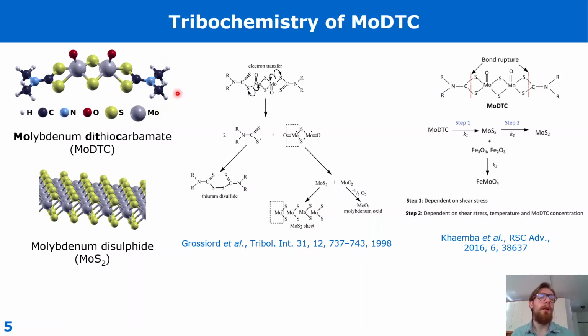computational cost. However, these molecules typically have longer alkyl chains. One of the first mechanisms proposed to describe the dissociation of MoDTC shows that the initial step of the decomposition takes place by breaking the sulfur and molybdenum bond. And then, after some steps, we obtain the beneficial MoS2 tribofilm. Another study, based on vibrational spectroscopy, proposed that the first bonds to be broken are the ones between carbon and sulfur. So this is a debated issue in the literature.